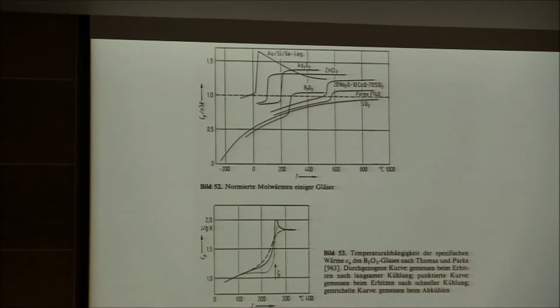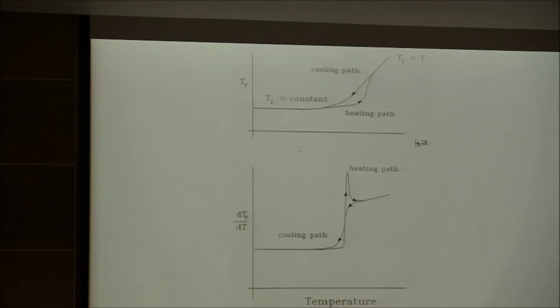The structure doesn't change. The structure is amorphous all across the diagram, but the structure is frozen on the left-hand side, and the structure awakens at that jump and then participates in the further energy cost of heating up the liquid through diffusion and through a redistribution of the structure of the liquid. And that costs energy. So if we can capture the details of this transition, maybe we can say something about the conditions under which the glass was formed. And the basic idea is this. You have the state of the glass, density, enthalpy, you could put any thermodynamic property in here, and you plot it versus the temperature.